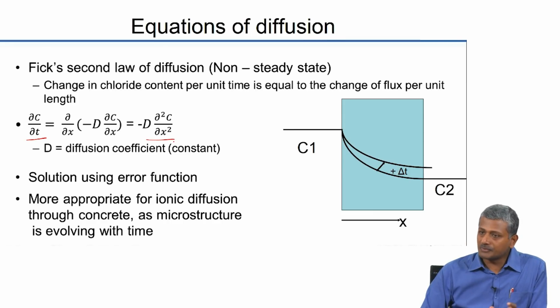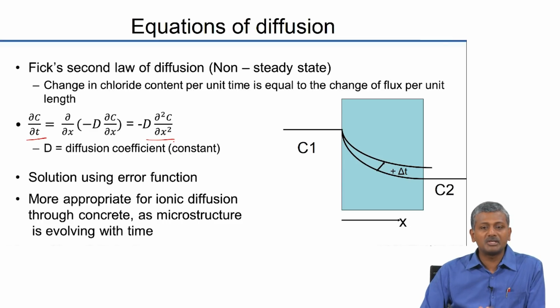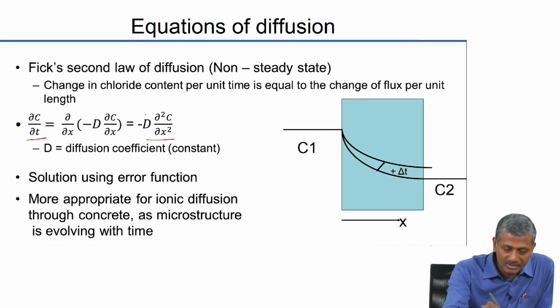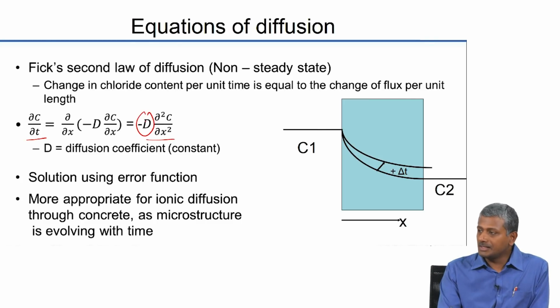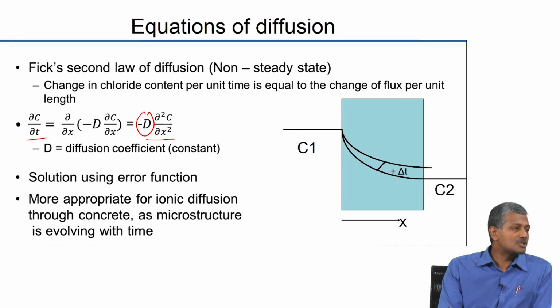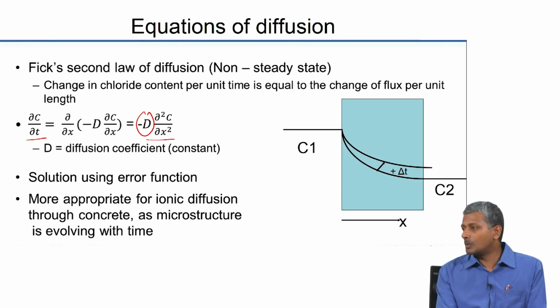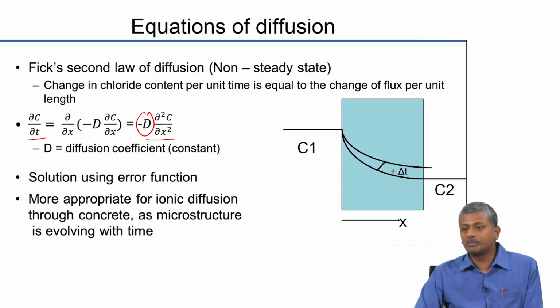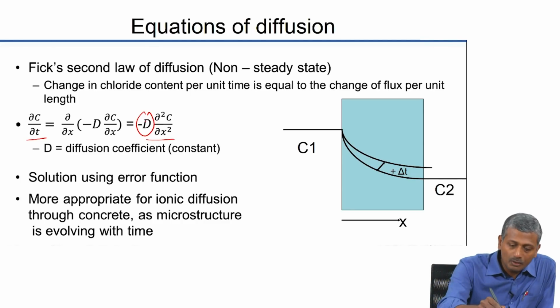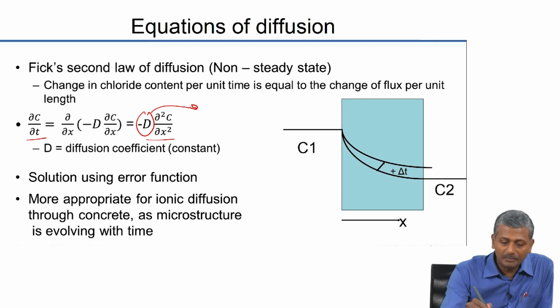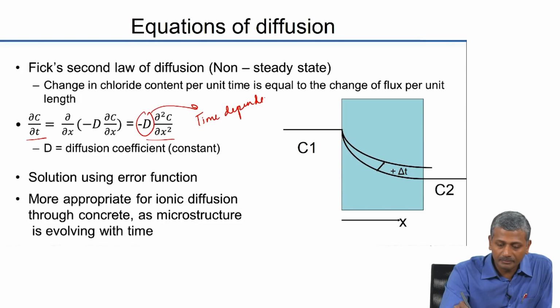Now as we discussed yesterday, the solution of this PDE requires the use of an error function, but one important aspect to understand is this factor D, which we otherwise call a diffusion coefficient, that itself is something which is not going to be constant throughout the service life of the concrete. Because what you measure at 28 days may be quite different from what you measure at 56 days or 90 days or 1 year, okay. So this value of D also is evolving with time. In other words, D is basically a time dependent diffusion coefficient.